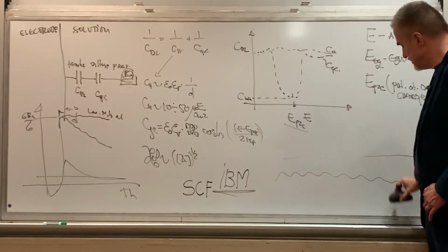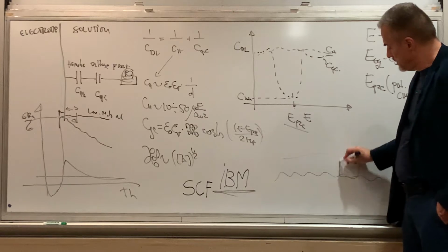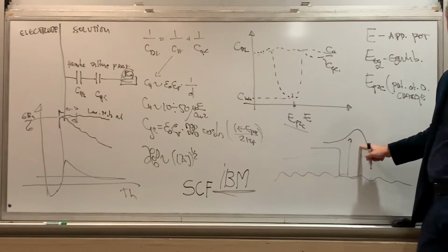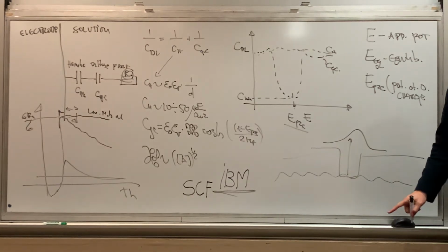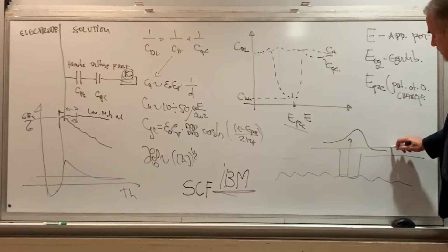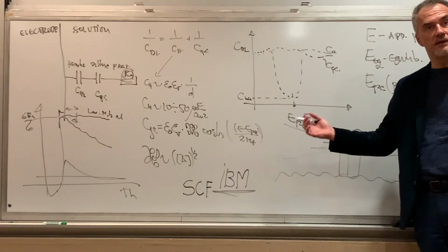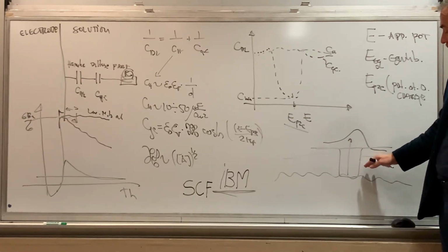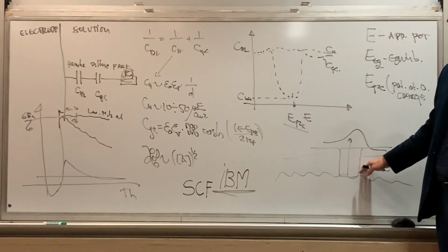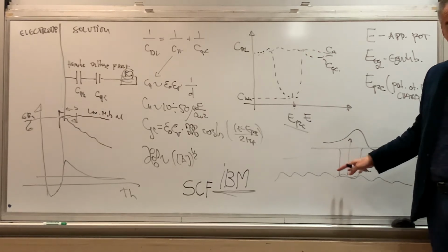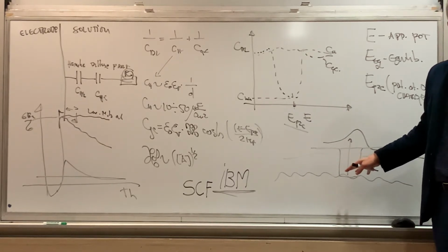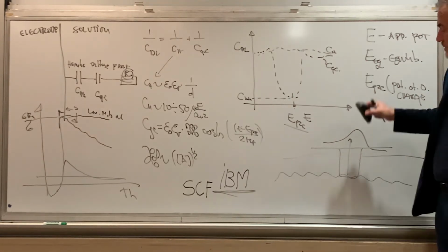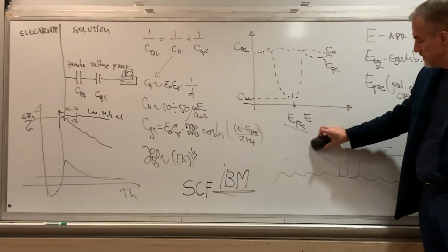What you really get is that this gets filled up and you end up with even an extra bump here with copper. And then you CMP, or chemically mechanically polish, and this is your copper line. And that's what 99.9% of electronics today, meaning integrated circuits, transistors, or everything else, is connected with: these copper lines produced by electrodeposition. So that's the golden age that happened in the 90s, and the magnetic recording industry also had